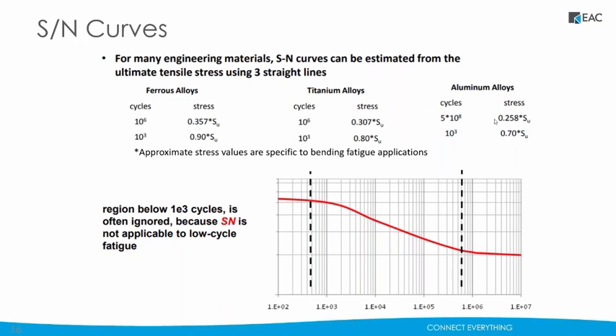And these constants are maybe ones you've all seen before. So under steel, 0.4 is the number a lot of people use. 0.357 is a little more accurate for the ratio between endurance limit and ultimate tensile strength. And aluminum is even lower. So different materials you'll find will have a pretty consistent ratio between those two values.